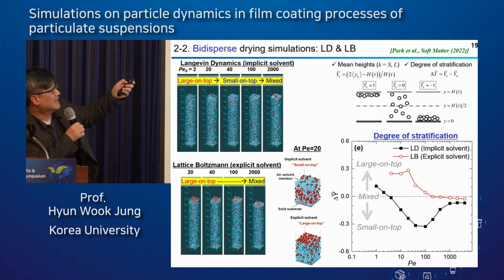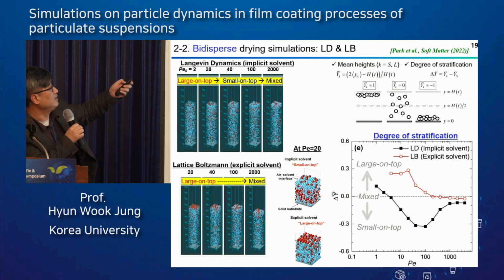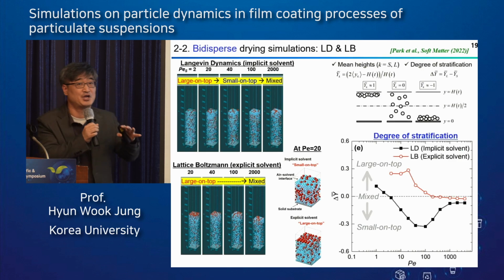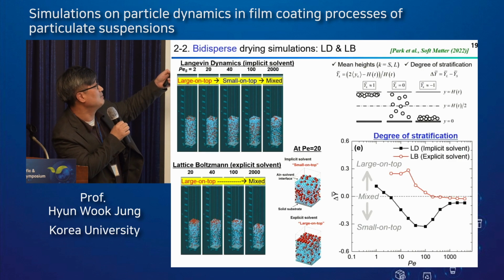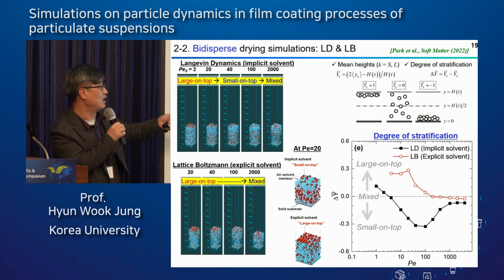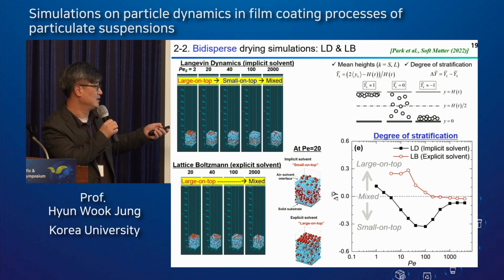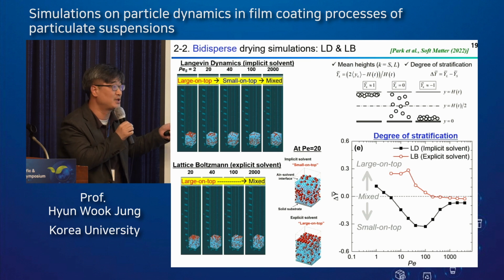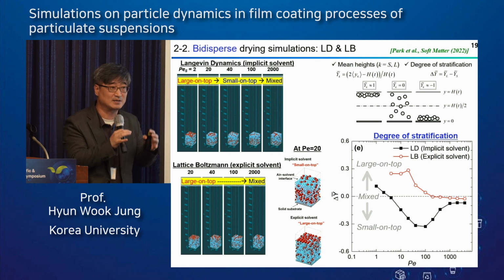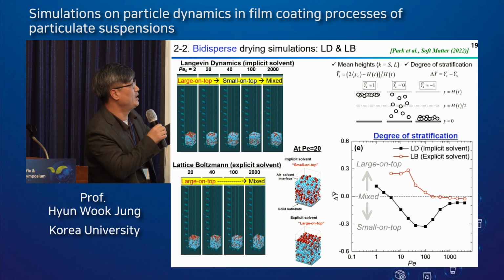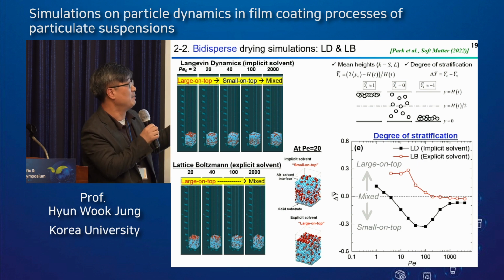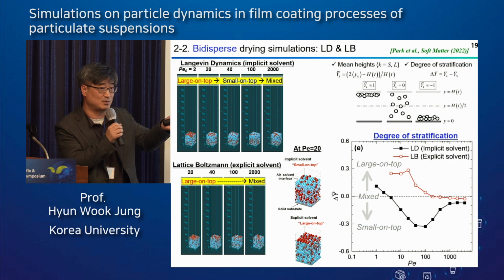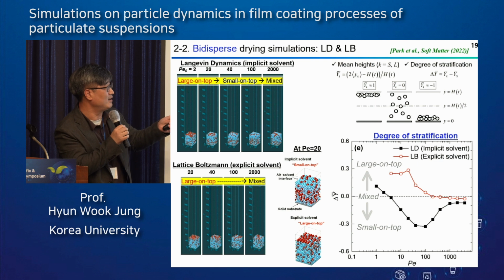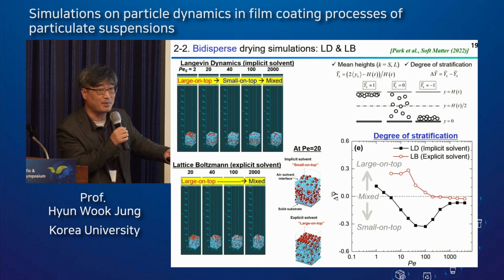So when the Peclet number increases, LD, the implicit solvent method, shows the change of stratification from large on top, to small on top, and mixed case. Whereas the LB case shows the change of stratification from large on top to just mixed case, suppressing the small on top cases. So we especially measured the mean height of large particles and small particles at the final stage. And using this data, we constructed this degree of stratification along the Peclet number.